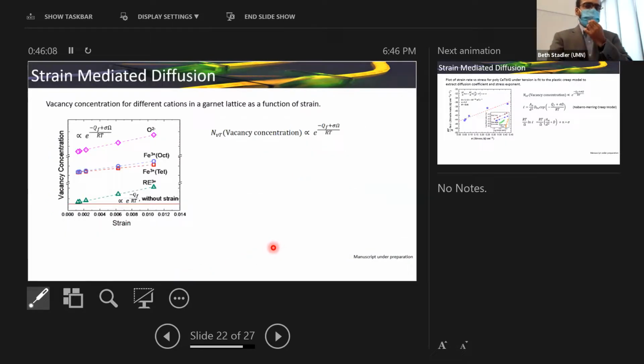So the first thing that I want to show you here is that the vacancy concentration is exponentially related to the tensile strain at the interface. As you can see, when we increase the tensile strain, which we basically do by increasing the thickness of the film, we are able to create a larger vacancy concentration for the different cations in the garnet, and also for oxygen. The baseline without strain is this red solid line at the bottom.